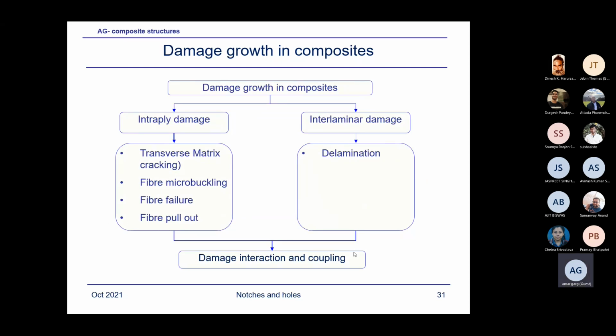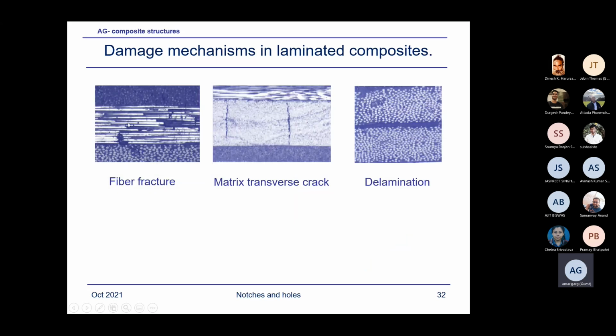Damage growth in composites can occur by intraply damage or interlaminar damage. Intraply damage, that is within a ply: transverse matrix cracking, fiber microbuckling, fiber failure, fiber pullout. All these modes are considered when people have modeled the damage growth in composites using the finite element method. There are lots of methods available, but not a closed-form solution, by the way, for any of this. Interlaminar damage, the delamination, and damage interaction coupling. Some are just pictorial presentations, like fiber fracture, matrix transverse crack, delamination.